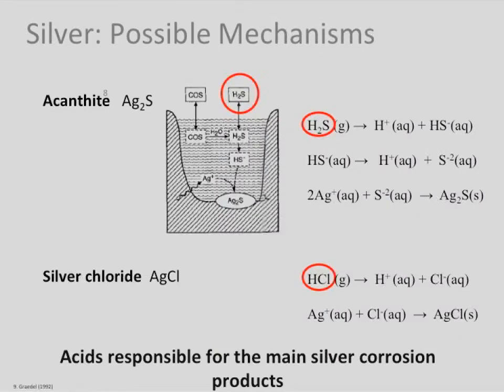I think most people know that hydrogen sulfide is a good source for sulfide anions, and it's the same process. You have a hydrated layer on the surface, hydrogen sulfide hits that surface, disassociates, and you end up with silver sulfide. But it was a weak acid that started that process.